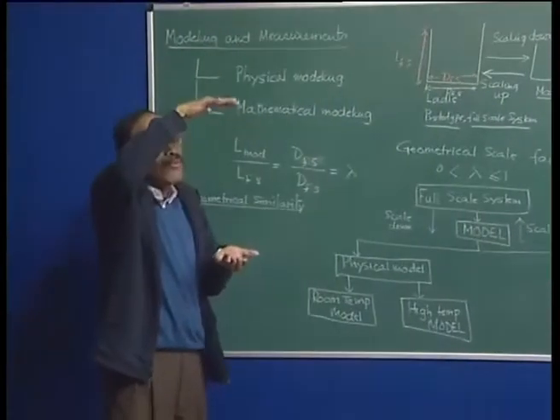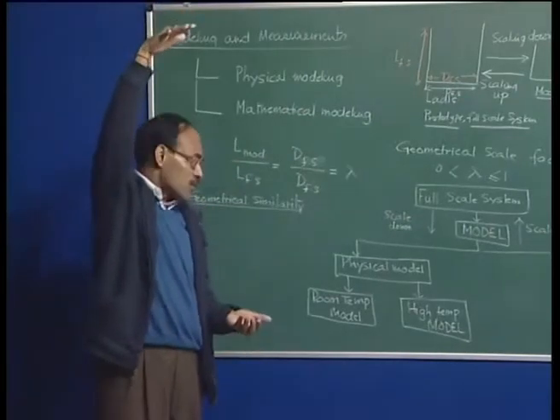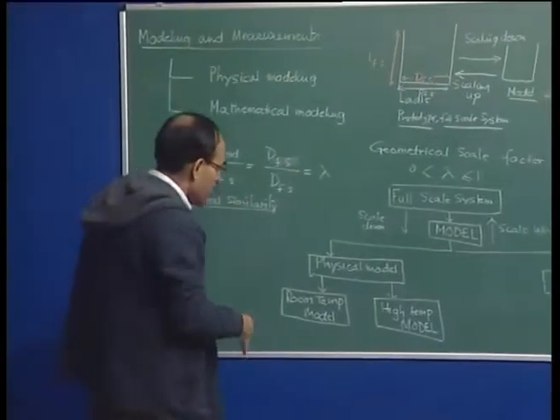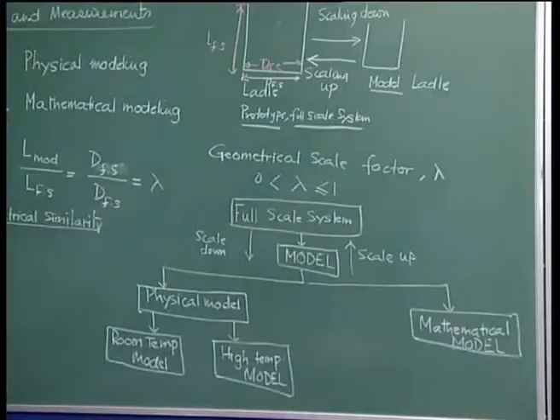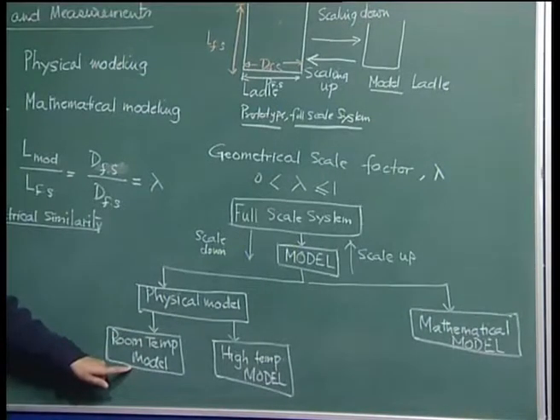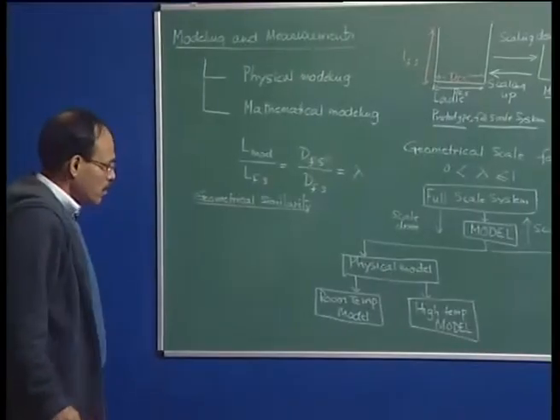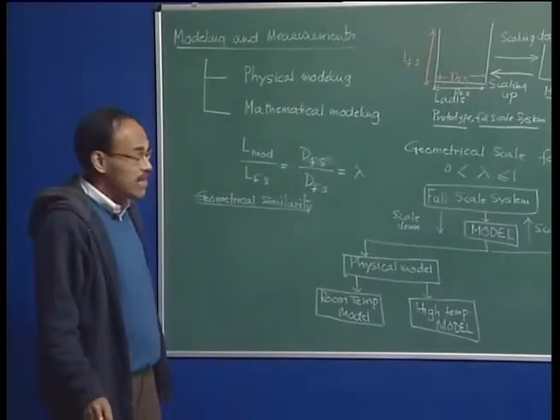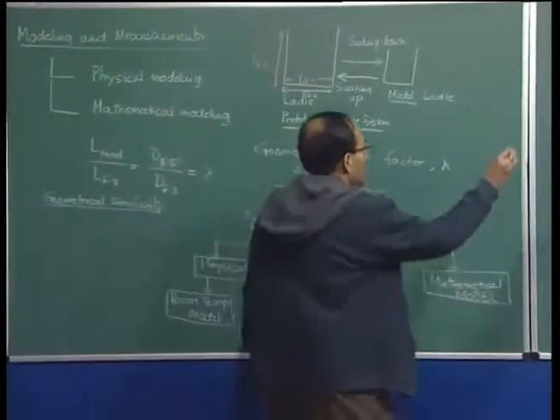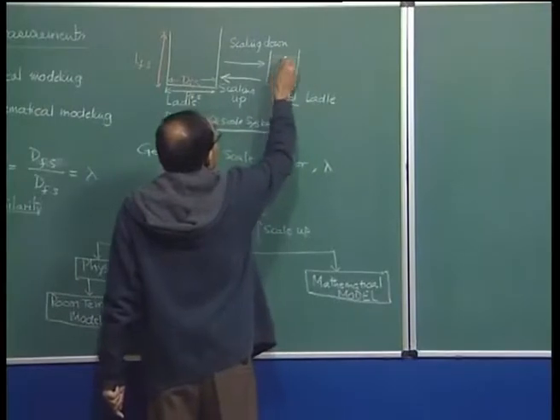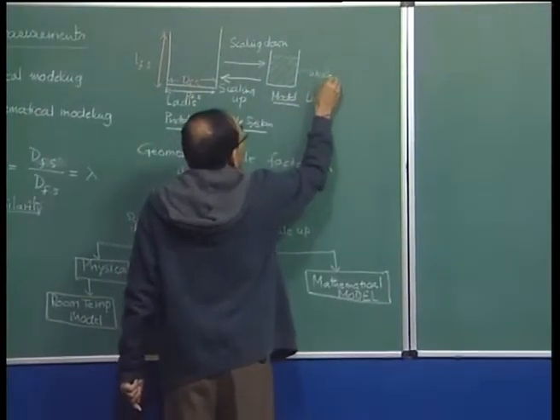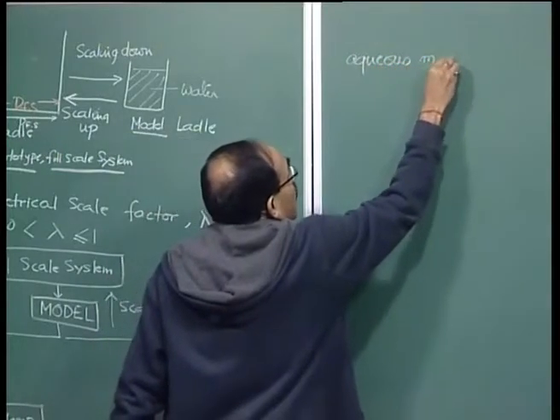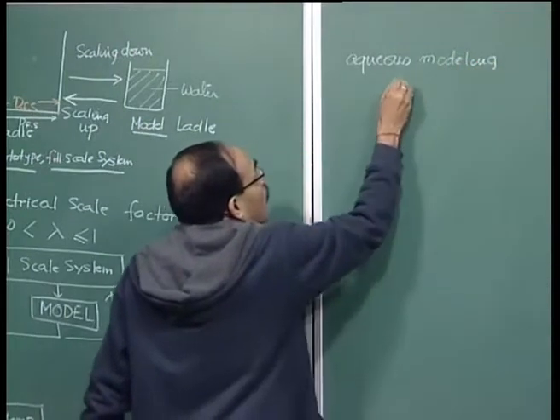For high-temperature models, we have various options: a small system filled with molten steel, a pilot-scale system with λ of perhaps 0.5 to 0.7, or a laboratory-scale system with λ of 0.2 to 0.3 filled with molten steel or with Wood's metal. These all deal with molten metal, so they are grouped under high-temperature modeling. Room-temperature models use mercury or water. Water-based models are extremely popular in steel making.